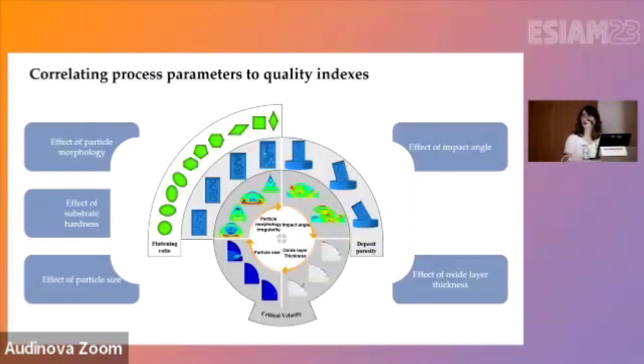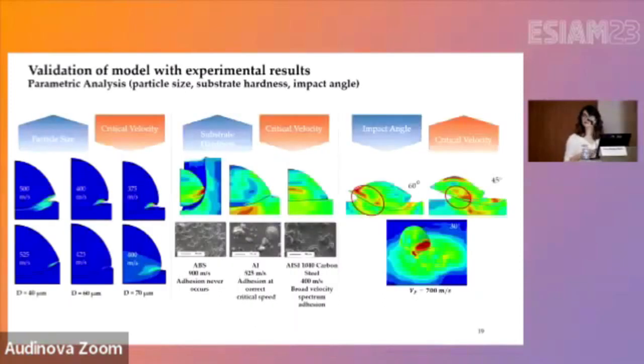and also on multiple particle impacts in order to see the effect of all these parameters on the porosity of the deposit that we get during cold spray, the angle of impact, and the morphology, how they affect the porosity. We have validated the model using some experimental tests to see the effect of particle size on particle velocity, critical velocity, effect of substrate hardness on the critical velocity, or angle of impact on critical velocity.